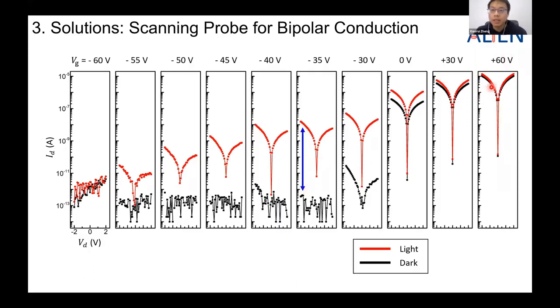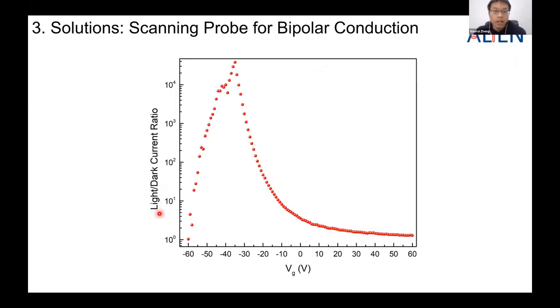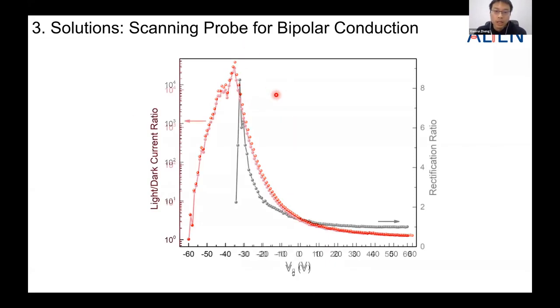And once we increase the backgating, the dark current and light current are almost the same. Only at this point they have the largest contrast. Okay, so if we further plot the light and dark current ratio as a function of the backgating, we still observe a similar phenomenon that there's only one peak here at a certain backgating, where the tip-induced p-n junction dominates, so that we have the strong p-n junction only at this point. If we also plot the rectification ratio in the same figure, we can see that they are basically consistent here.